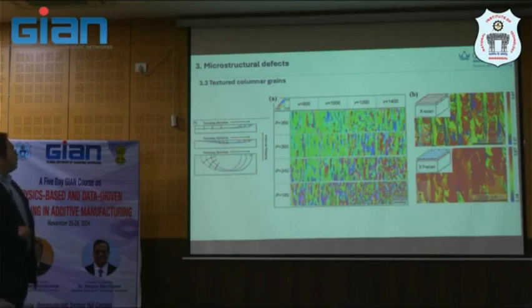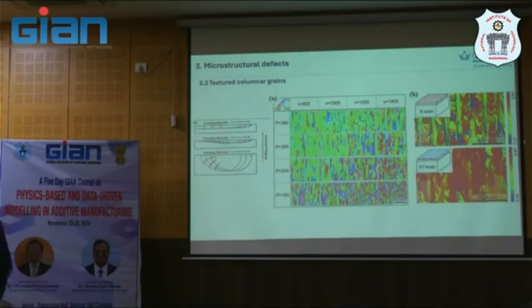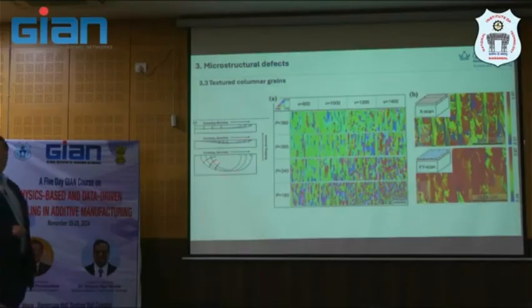So as I said to you, this is related to the simple thermal model as well. If you scan like this, the microstructure will grow this way, so we can control the directional growth of the material. But if you scan like this, the microstructure may start to bend a little bit. But if your scan direction makes this melt pool very hemisphere kind of shape, the grain will grow in this direction. That's how you see some feature like this in the melt pool, for example.